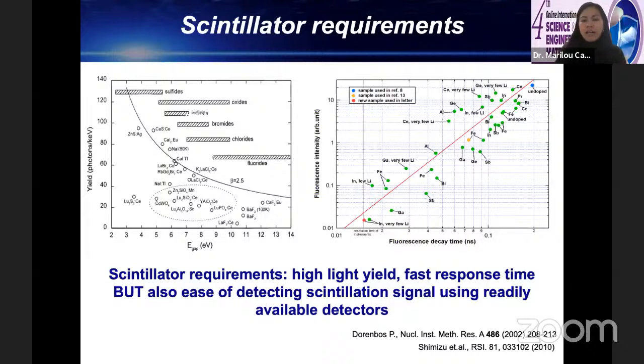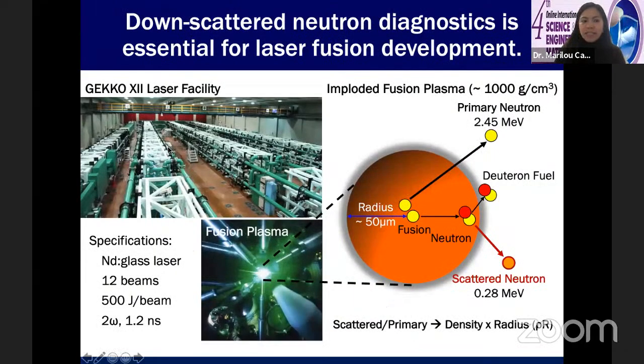For our particular work, for our application, we're interested in developing scintillators for detecting neutrons in laser fusion. So this is the laser fusion GEKKO XII facility at Osaka University. It consists of 12 beam lines. So each of these green pipes corresponds to a laser beam line. There are 12 beam lines from an Nd glass laser. And we focus these 12 beam lines into a 50 micrometer radius spot. And in this very small radius and very high energy laser beam, we generate fusion plasma. As shown, this bright spot here is the fusion plasma that's generated.